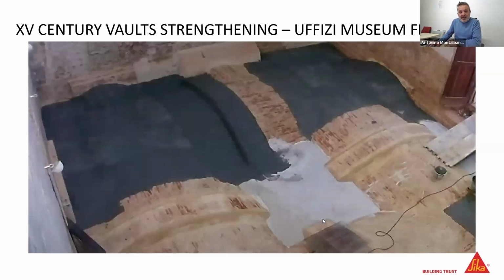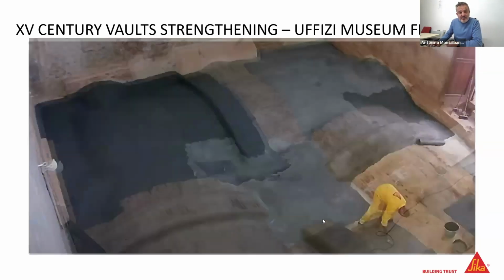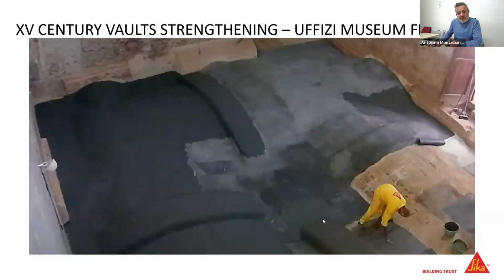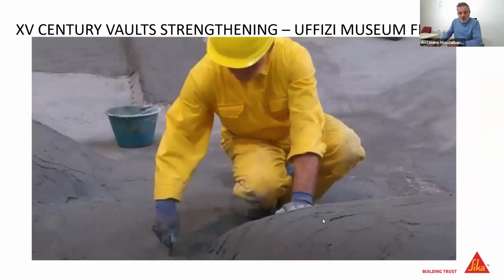And in this case, we applied a glass fiber grid that we embedded in an inorganic matrix, and you can see the phase of application where the total thickness of the system is around 10-12 millimeters, and we embed this grid to strengthen and improve the load-bearing capacity of these vaults.